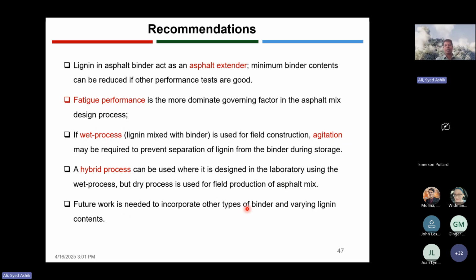But our recommendation is that we should use a hybrid process for design and construction. During design, we can add lignin to the asphalt binder, modify the asphalt binder, and do the design. But when we want to use it in the field, we can use it using the dry process. Use it through the RAP port. If we add lignin through the RAP port and have our asphalt binder come through separately and then do the mixing, that could be one way to get away with this agitation and the storage stability problem.